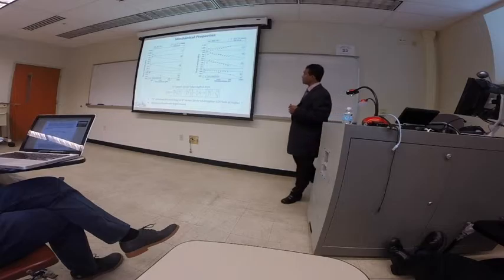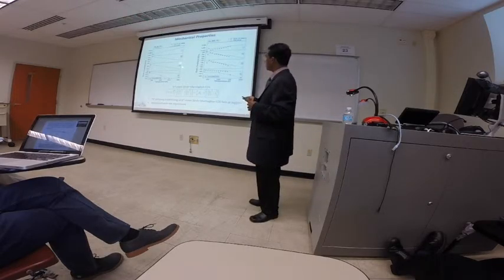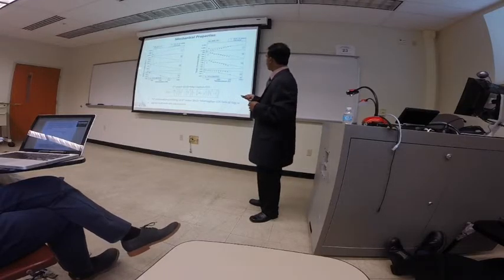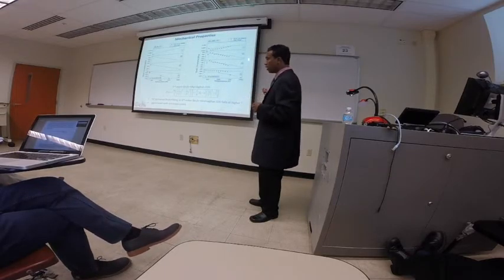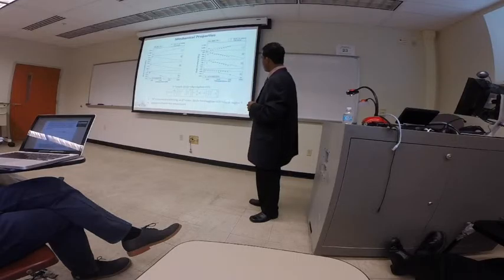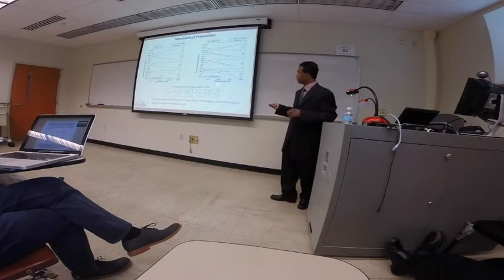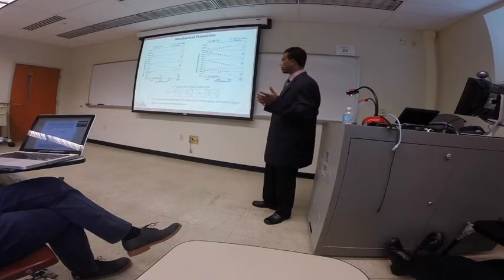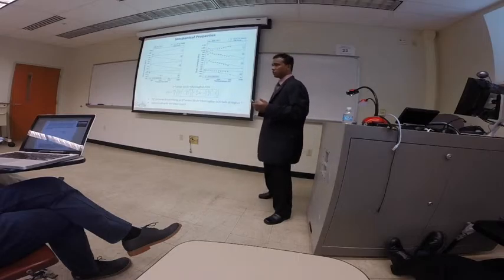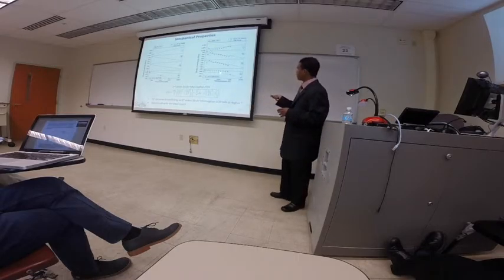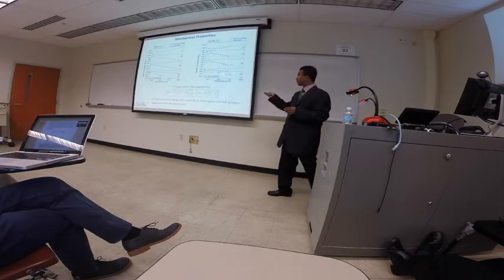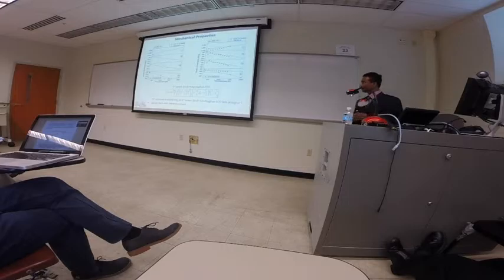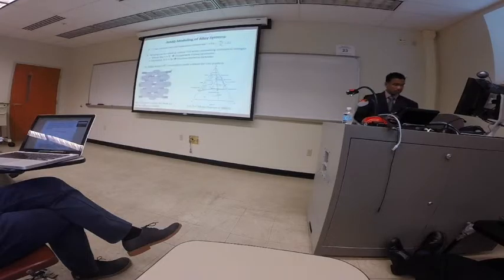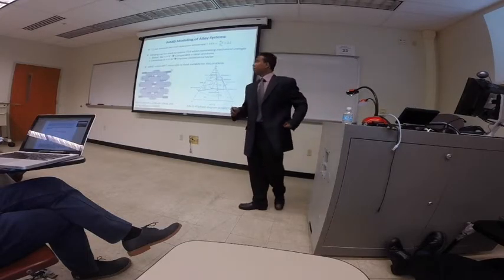And also the same case with the average or bulk mechanical properties: bulk modulus, shear modulus, Young's modulus, and Poisson ratio. The T1 phase agrees well at room temperature with the experiment, and T2 phase agrees well with the experiment as well. And as I said before, the technique used before, calculating a ground state structure and extrapolating with maybe a fit to the equation of state, is good up to a certain temperature, but then it starts to fail. And we proved that a direct method is much more suitable, effective and accurate to do this kind of simulation. Then we used ab initio MD for alloying.